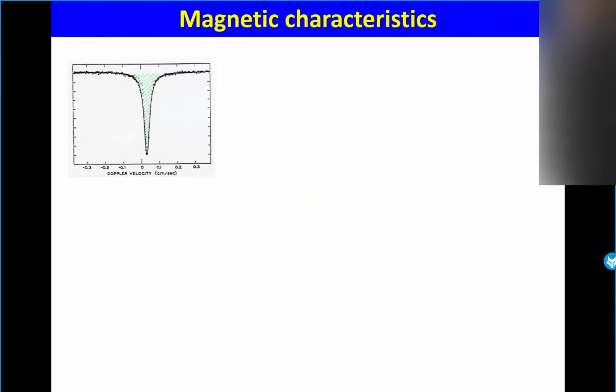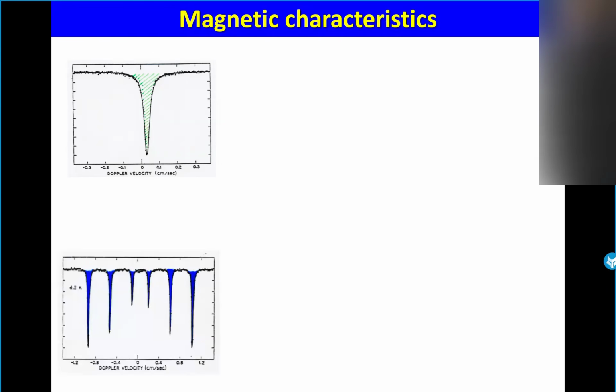So those studies were done in the 60s and 70s, and this is to show you the possibilities of Mössbauer spectroscopy. Above 363 K, you have a single line. But this single line is not a pure single line. You have a small quadrupolar splitting, if I remember, 0.08 millimeter per second. That means you have a small breaking of symmetry around the iron nucleus. If you decrease the temperature, you will get a nice sextet at 4 K. But you are not able to conclude ferro, antiferro, other.